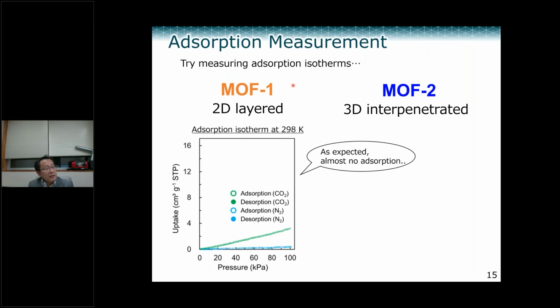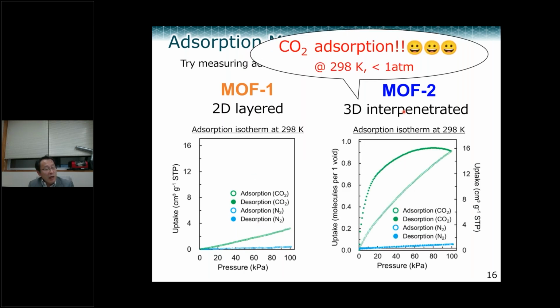So Shimada-kun tried to absorb gas anyway. In the MOF1 case, the 2D MOF case, as we expected, no sorption occurred for dinitrogen and CO₂ either. So, a somewhat reasonable result. However, surprisingly, in the MOF2 case, there was no nitrogen sorption at all. However, in the CO₂ case, absorption occurred. And also, as you can see, large hysteresis was observed here. So we wondered what's going on here.